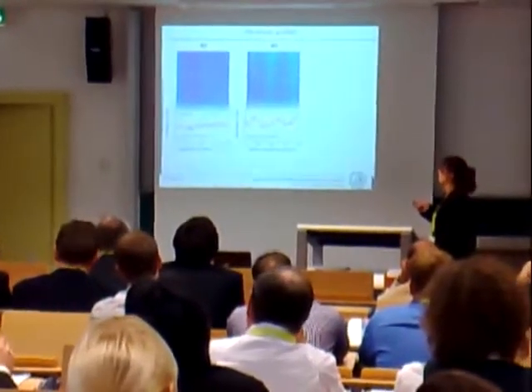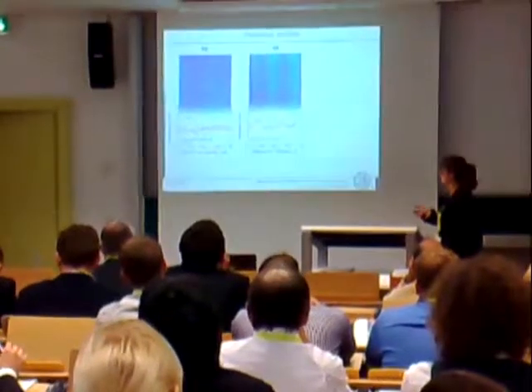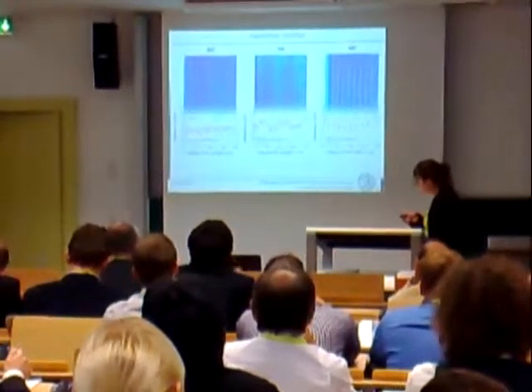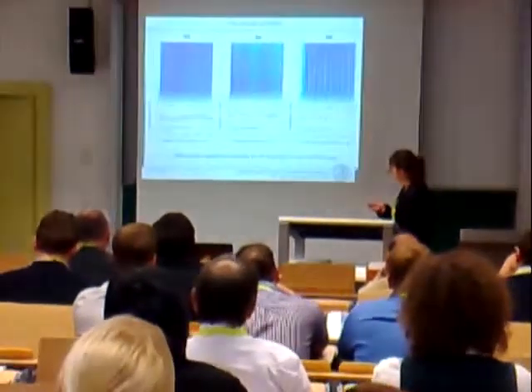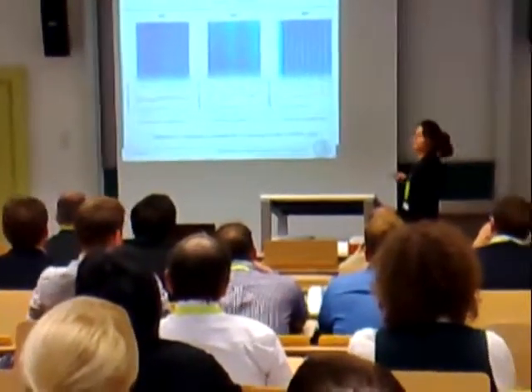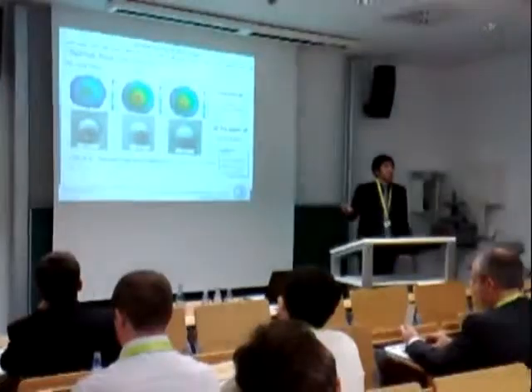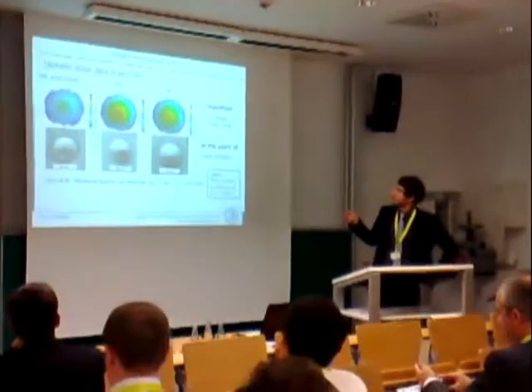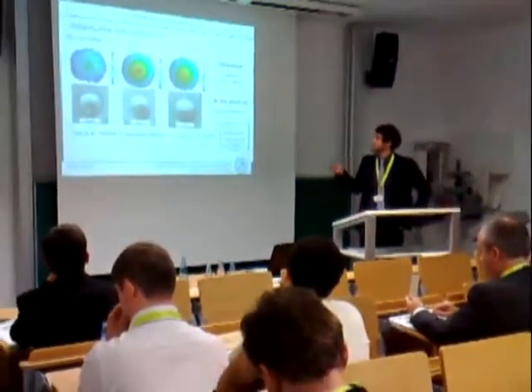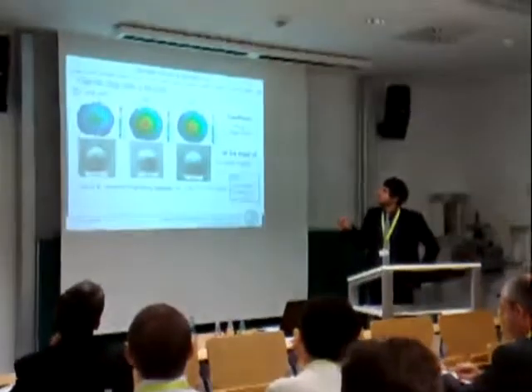4 cycles, you can see that the jump in hardness is increasing for these 2 materials. And always, the lower hardness is the 6000 alloy, the higher hardness is the 5000 alloy. For 6 ARB cycles, you can see here also these clear jumps. And what was obvious now is that the strength of the 6000 alloy is only increasing up to 4 cycles, is saturating after more deformation until the crack was formed. And when you take the color code into account, you can see that the other fine grained sheets show a much better deforming behavior than the cold rolled state.